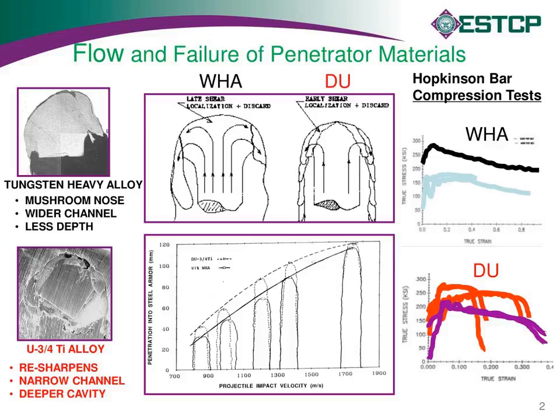If you look at the velocity, measured horizontally on that axis, it's still about a 100 meter per second shift between the performance of DU and tungsten, even at 1700 meters per second. What you're seeing really is that at the higher velocities, the early part of the penetration process is essentially hydrodynamic. Inertial forces are dominating the flow and failure of both materials, and you really can't see any difference. The two penetration tunnels basically overlay for the first half of that penetration process.